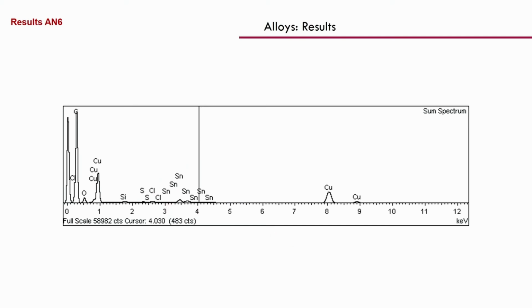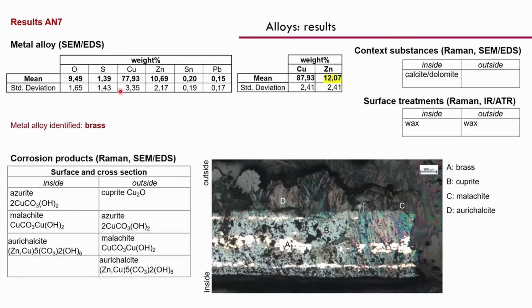I can continue because till now, as you saw, we analyzed a very defined alloy. So we analyzed only bronze, mineralized or not, and now we started to analyze brass. So the other alloy that we found is brass. As you can see here, we have 12% in weight of zinc. And even in this case, these slices are made by metallic brass, and all the other part of the cross section is mineralized. And even on this tibia, on this external part, we found wax as protective.